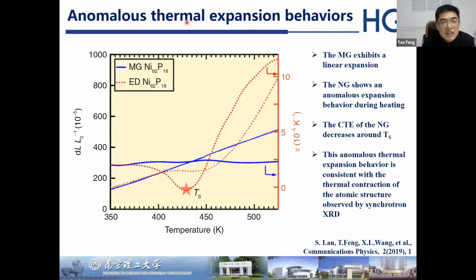And this is the thermal expansion experiment. From here, we can see the blue one is the metallic glass that shows a linear expansion. However, the red dotted line is from the nanoglass, and it shows an anomalous expansion behavior. You can see that around the temperature Ts, there is almost zero thermal expansion. And this anomalous thermal expansion behavior is consistent with the thermal contraction of the atomic structure which we observed from the synchrotron XRD, as we showed you before.